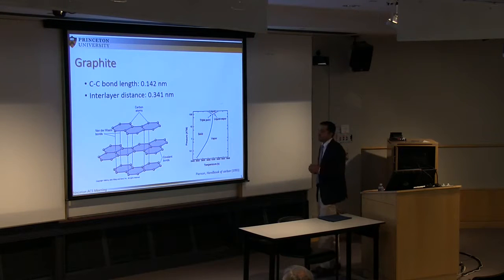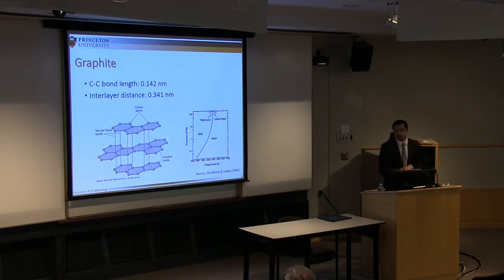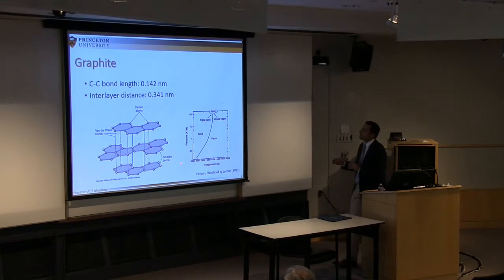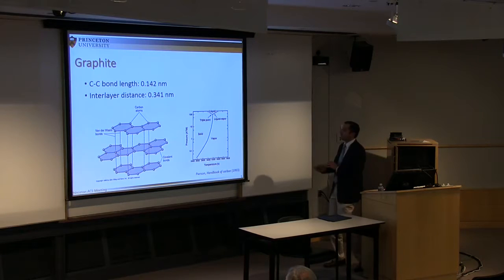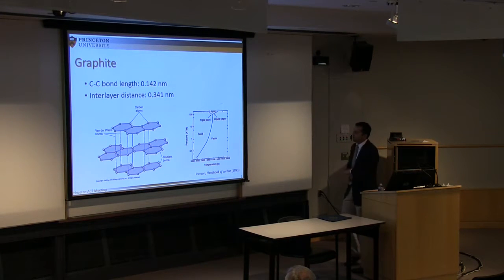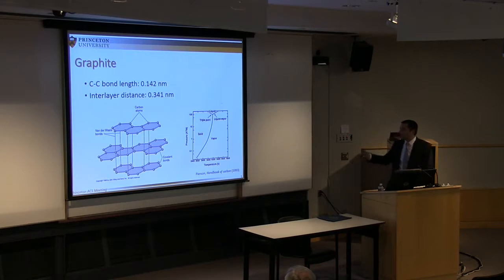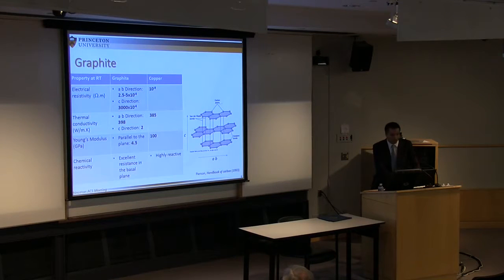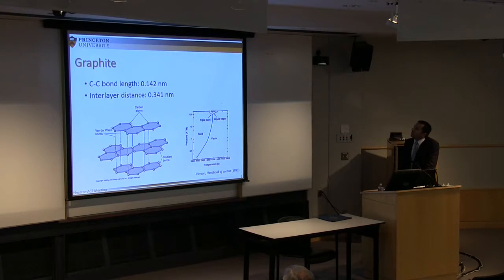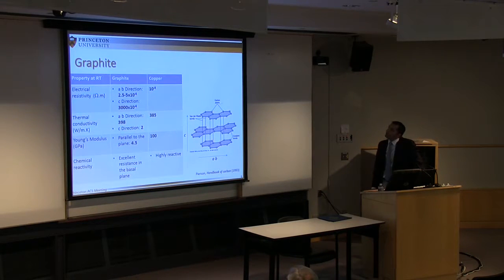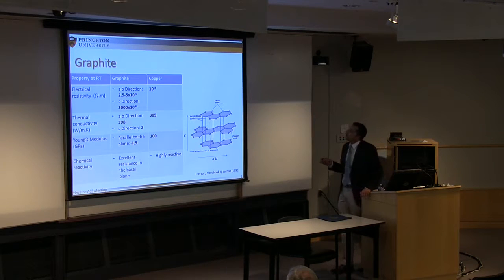I said graphite has many interesting properties. It's because of the physical and chemical properties that it has. As you can see on this phase diagram, it's stable up to almost 3,500 Kelvin, which is an extremely high temperature. So it's clearly one of the most stable materials, at a reasonable pressure. And when you go even higher in pressure, at sufficiently high temperatures, you can even synthesize synthetic diamond. So now, if we look more carefully at the properties,